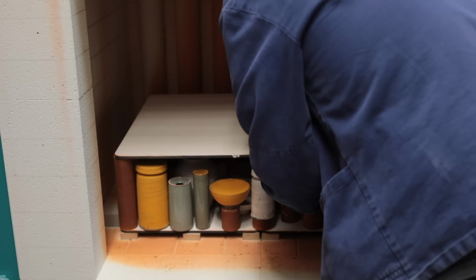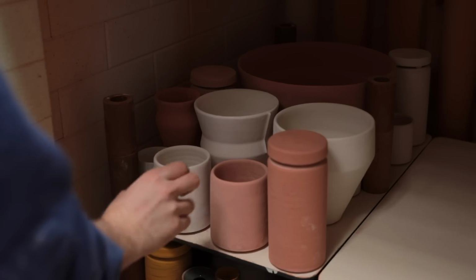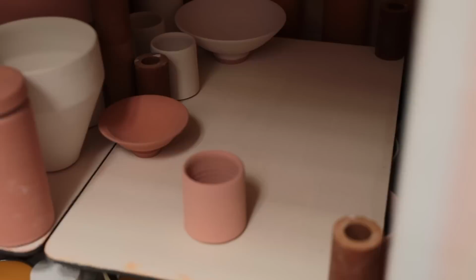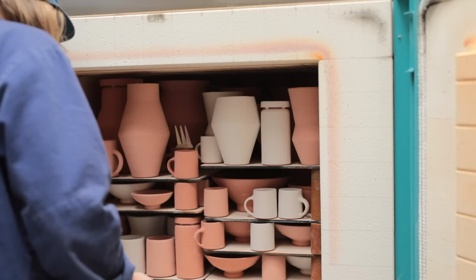After each layer has been densely filled, two more shelves are placed in, atop props, and another layer of pots can be packed in. For this second glaze firing, which goes to a much hotter temperature, the pieces cannot touch, otherwise they'll fuse together. Yet it helps, when reduction firing, to pack as densely as possible, so there's as little space for oxygen to occupy, as ultimately during the firing we'll be trying to starve the kiln of oxygen. And if I pack the kiln and leave lots of empty space, then that space oxygen can easily fill, and I'll then have a much more difficult time achieving a successful reduction atmosphere. And if the reduction is unsuccessful, then none of my pots will fire like I want them to.